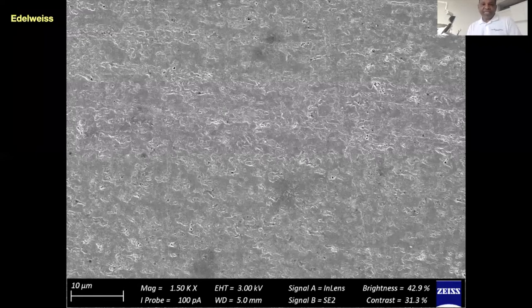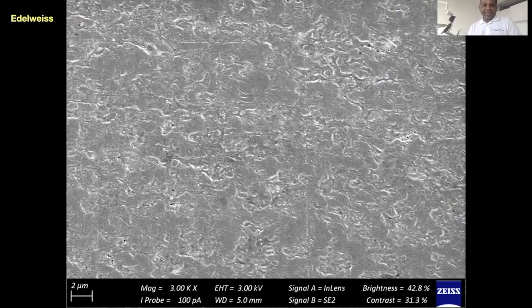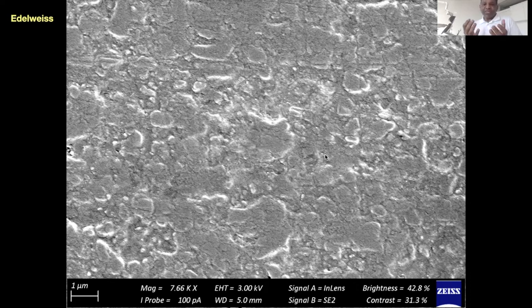Compared to Edelweiss — again, not worked on, placed directly on the microscope at 1,500 times — it appears to be pure glass with maybe just a small defect, but generally a smooth, clean surface. At 3,000 times, similarly no defects are present — just a single glass face on the surface. At close to 8,000 times, again pure glass single face. Because of the absence of any voids or defects, this Edelweiss CAD CAM block will not take up any stains.